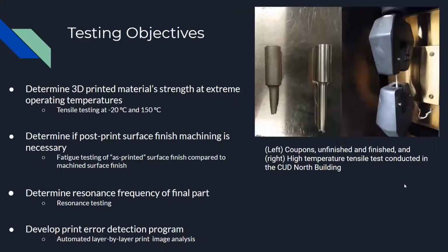So, material testing. Given our design requirements, we determined that we had four main testing objectives. The first was to determine if the 3D printed aluminum meets the strength requirements throughout the anticipated operating temperatures. Two, to determine if surface finish machining is necessary in order to preserve part integrity. Three, to determine the natural resonance frequency of the final part, where it's greater than 20 Hertz. And finally, to develop an automated printed error detection program to determine whether printed parts have any hidden errors without having to perform destructive testing.